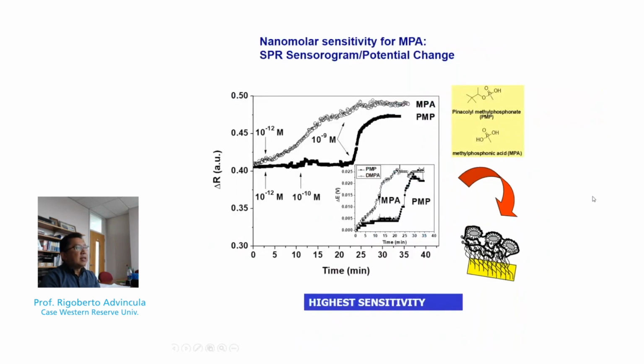And then finally, the nanomolar sensitivity was extended to what we call picomolar sensitivity by looking at the reflectivity change as well with a final breakdown MPA acid. So to summarize, what I've shown here is you can do SPR sensing towards a nerve agent.